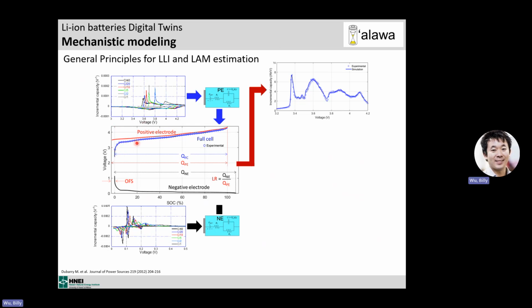Again, on the voltage capacity curve, it looks good, but I just showed you that that scale means nothing. And that's a lesson for modeling people. When you report the fit of your model, derivate the curve, because you can sell a really bad fit if you just show the voltage capacity curves. But if you derivate, you can see that we match pretty well all the different peaks in terms of position, shape, and intensity. So we replicate exactly the electrochemical response of the cell. We build a virtual cell that's identical to the real one.